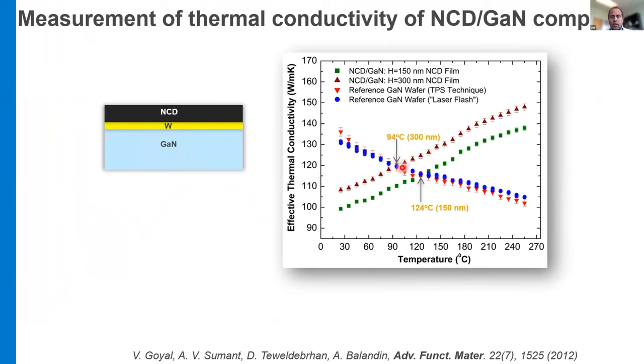So what you are seeing here is the effective thermal conductivity of the composite film. And then we use different thicknesses, 150 nanometer and 300 nanometers. And then what is plotted here in the blue circles is the reference gallium nitride wafers. And as you can see, as the temperature is increased, the thermal conductivity of the gallium nitride is reducing. But interestingly, when you look at the 150 nanometer, the thermal conductivity is actually increasing with the temperature, and that gap also increases as we increase the thickness of the diamond film.